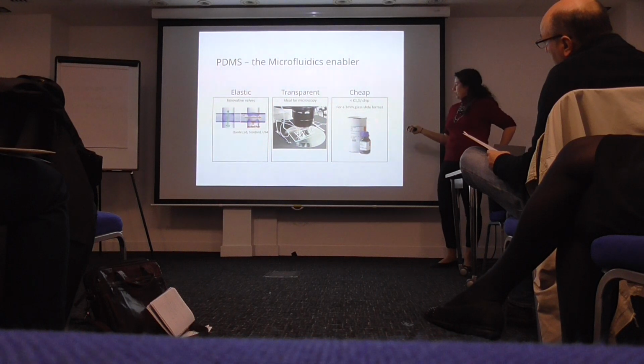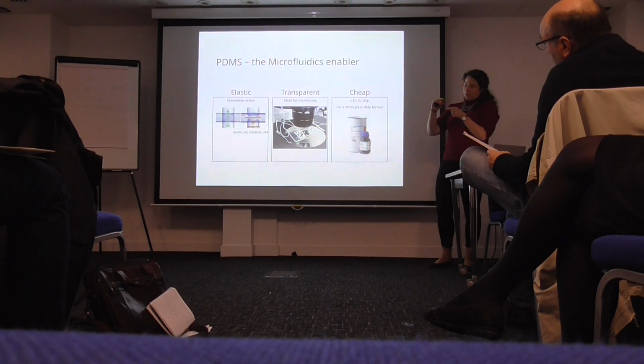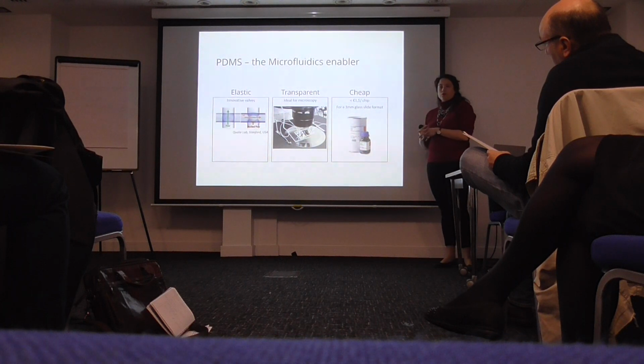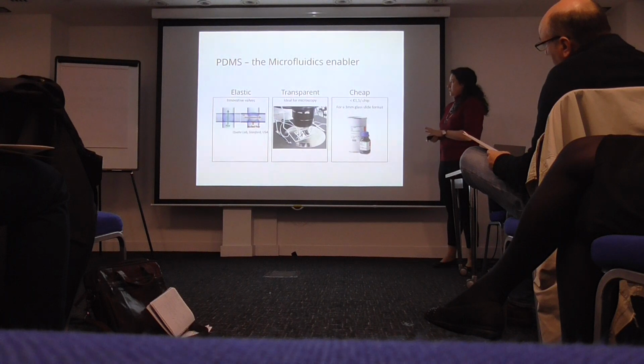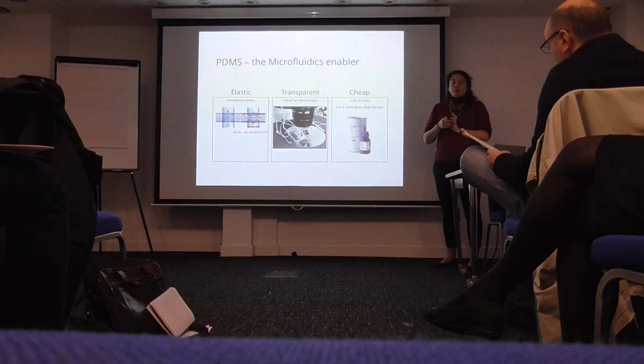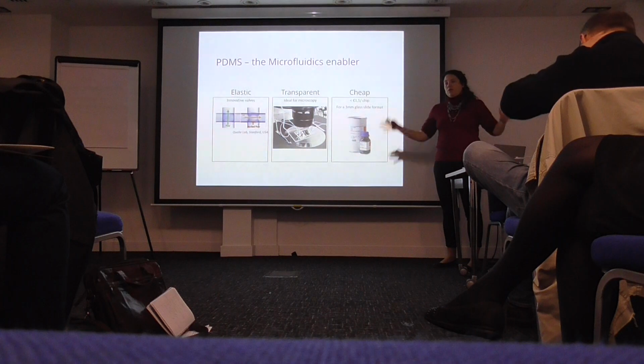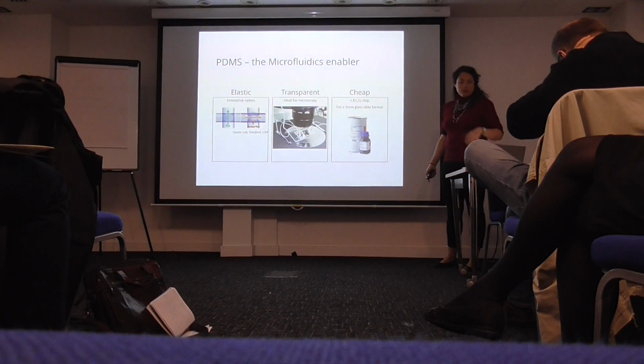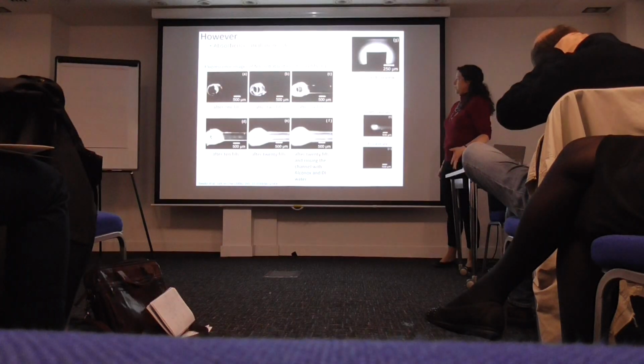If you take into account that you're getting one of those bottles and you're making a slide with a thickness of 3 millimeters, you end up paying less than 1.5 euros, which is just above £1. So it's a very cheap system. Now, the problem is that as a result, it's taken over the microfluidics world, and a lot of people don't realize the problems of PDMS.